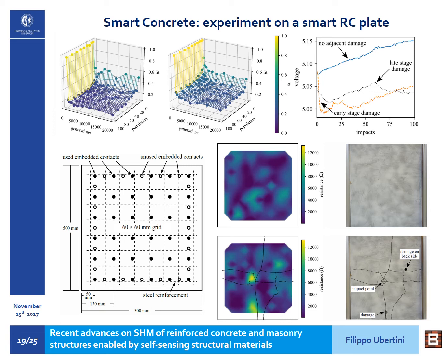And in particular, we show on the bottom right of the slide, on the upper diagram, the contour plot of the identified resistor values for the undamaged plate, where of course we see that there is some difference from one point to another, probably due to a different quality of the dispersion of the nanotubes and possibly associated to a slightly different moisture content in the material.